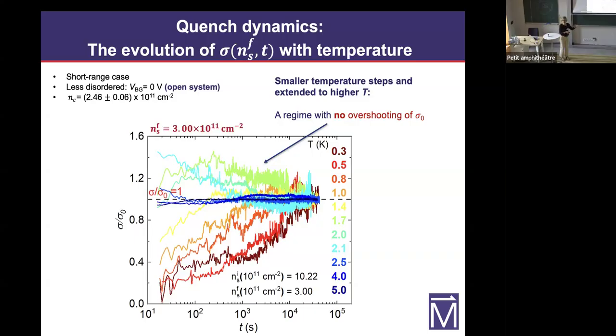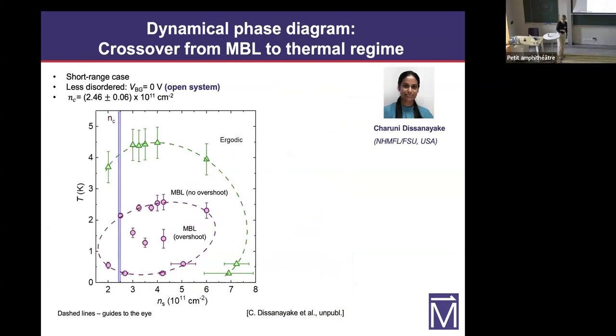We have obviously hundreds of such measurements. We've done it again for different densities and temperatures, and we are able to create a dynamical phase diagram as a function of temperature and density. So these are the latest data. As I've labeled here, the dashed lines are guides to the eye. This purple region is a region where we observe this overshooting. And then we have this region that surrounds it, where there is no overshooting. We still see the same type of relaxation. And then at higher temperatures and densities, the system is in thermal equilibrium.